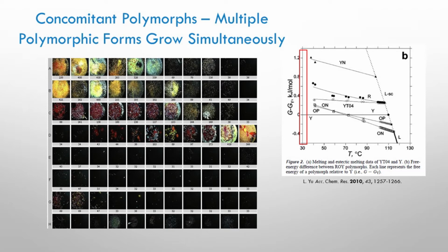But at this time, he'd use a combination of thermal analysis at the melting points and their enthalpies of fusion, relative to the room temperature yellow form, which was stable at room temperature, he could infer the free energy, or measure the energy difference between the different polymorphs.